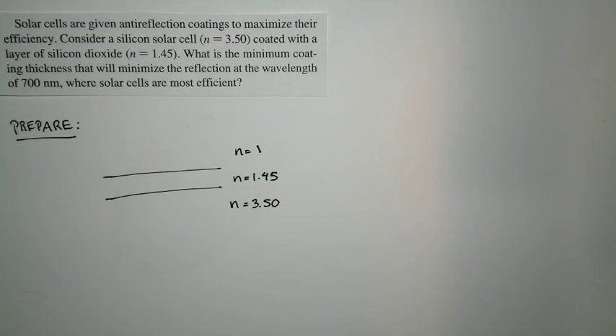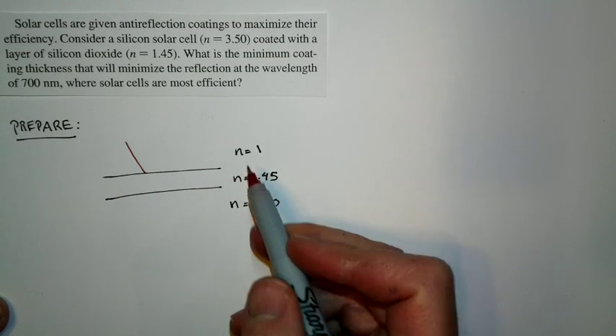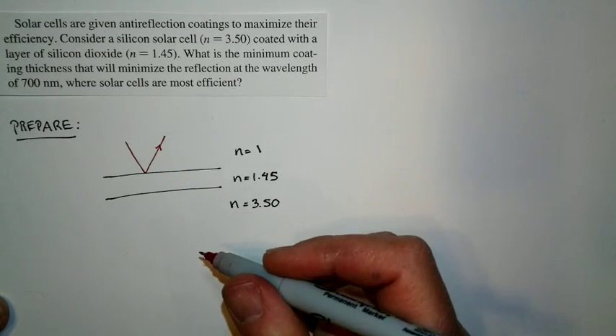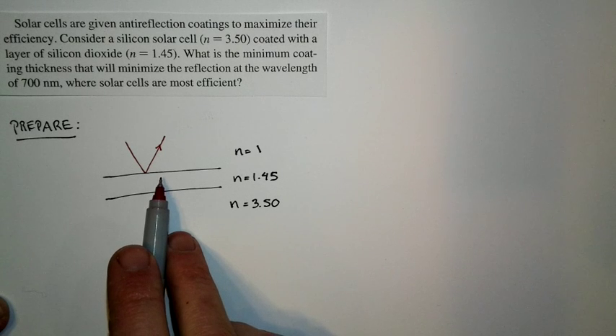Now light comes in. And when light comes in, let's draw a picture of a ray of light coming in, and it's 700 nanometers, so we'll choose red, and it hits this first surface. It's going from air, n equals 1, into silicon dioxide, n equals 1.45. There's a change of index of refraction, and so therefore there will be a reflection. And it's also going to change the phase because the index of refraction increases.